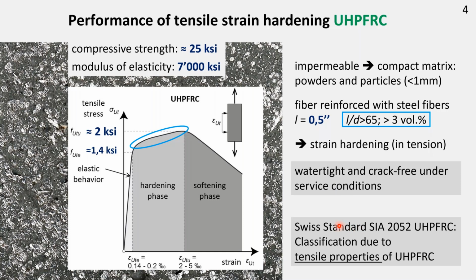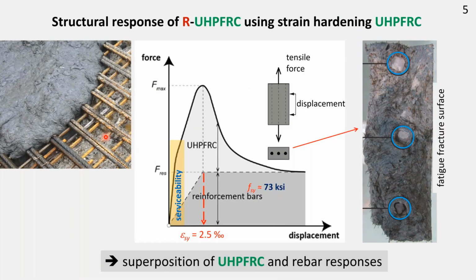And I would like to mention that in the Swiss standard, we classify our UHPFRC as a function of the tensile properties, not the compressive strength. Now, it is very advantageous to combine UHPFRC with steel reinforcement bars that act in the main stress direction. It is very economic to do that cost-wise, and also from a mechanical viewpoint, it's interesting. And when we analyze this section consisting of steel rebars and UHPFRC, it is quite easy to do. It's simply the superposition of the UHPFRC and rebar responses.